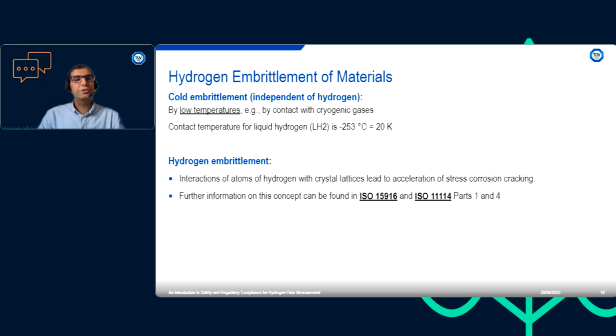Another safety concern with hydrogen is hydrogen embrittlement of materials. Hydrogen can cause embrittlement in 2 different ways. The first way is when we are dealing with liquid hydrogen. Because it has such a low temperature, that temperature reduces the ductility of any material that comes in contact with the hydrogen. And then it can increase the risk of cracking and the failure of the material.